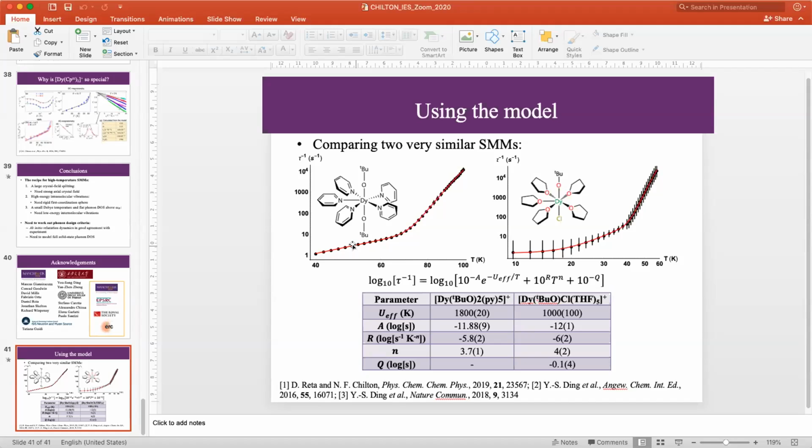I think these are the key, because all these phonons due to molecular rotation basically cause all these direct processes. You have an anisotropic G tensor which rotates in the field along a particular direction, and that rotation causes the fluctuation in the spin Hamiltonian that drives the relaxation process.